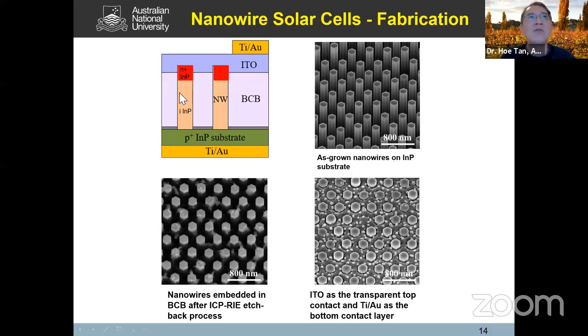And as you can see here, what we did was we planarized the nanowire array with some polymer like BCB. So obviously when we planarize it, you know, it covers the entire nanowire. And then we need to etch down the BCB such that only the top contact layer is exposed. Okay. And then once that's done, we deposit a transparent contact like indium tin oxide and then put another contact on the top and a contact at the bottom. And you can see here, these are different stages of the fabrication process here.